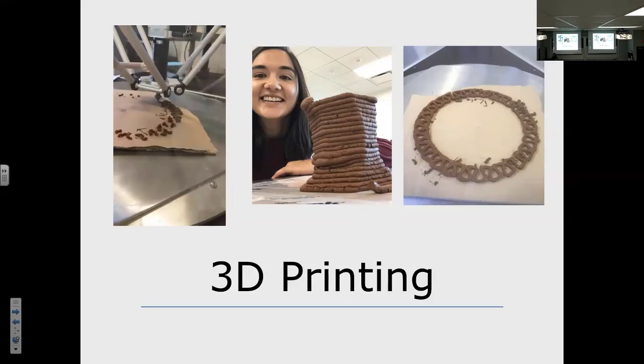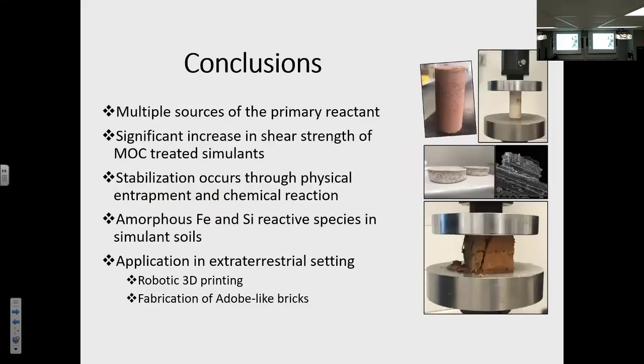So in conclusion, basically we decided to go with the magnesium cements because there are multiple sources for the primary reactants that go into a magnesium cement system. There's significant increase in the shear strength of all our magnesium treated simulants. Basically, when we looked at mechanism, when we tried to investigate, we think that it works through both physical entrapment as well as chemical reactions. And we believe that the chemical reactions are probably mostly between the amorphous iron and silica phases that are present in the simulant samples and the reactive species in the magnesium oxide itself.